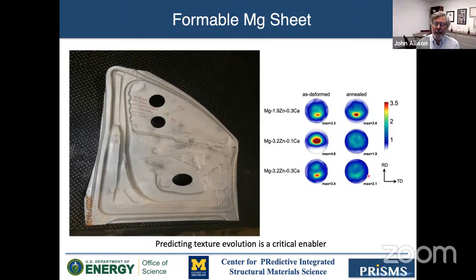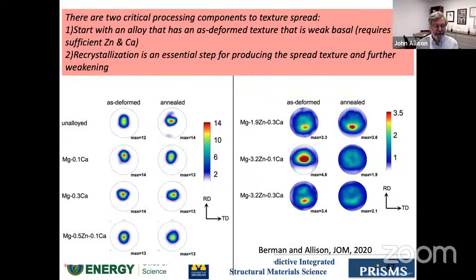And to get a formable alloy, you need to have very reduced textures, instead of these pronounced basal textures, which can be even... a pronounced basal texture would be like 12 or 14. But in these now rare earth or Mg-Zn-Ca alloys, what we've discovered also have these soft textures. So zinc or calcium alone don't do this, but zinc and calcium in combination provide these very weak textures. And as I said, this is very critical for sheet formability.